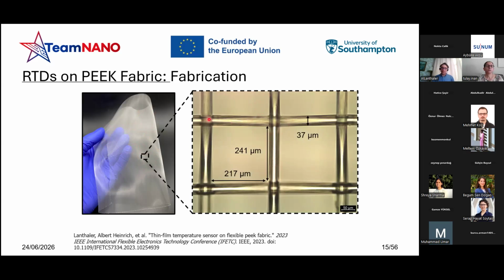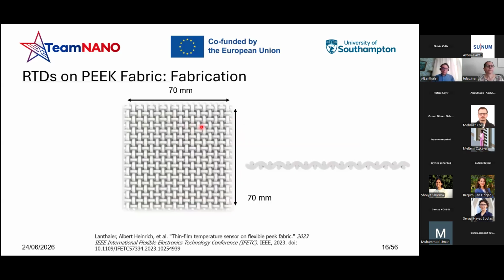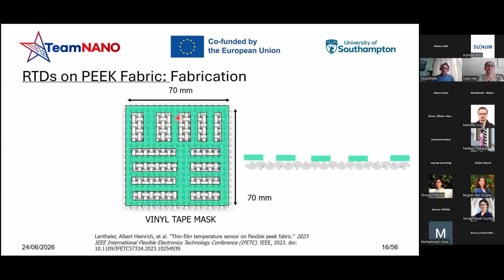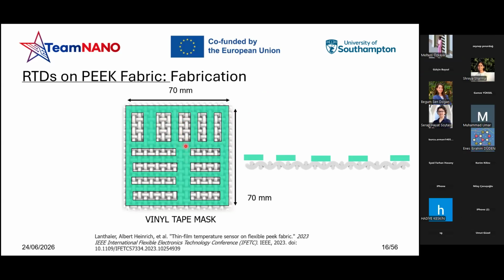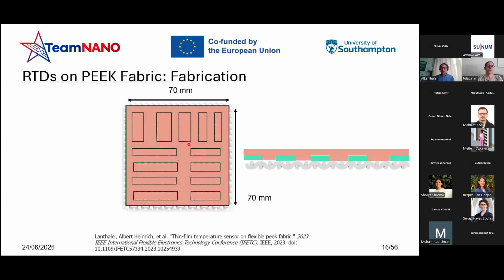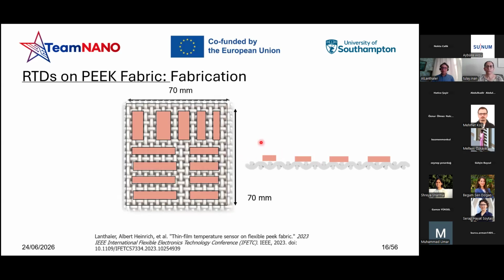As you can see, the lattice of the fabric is very broad, so it is pretty challenging for us to fabricate a continuous and smooth thin layer on top of this fabric. So what I've done, basically, I cut the fabric I mentioned before into a 70 by 70 millimeter square. I placed it into high vacuum condition in the sputtering tool. Before that, I taped it with a vinyl tape mask in order to have a better adhesion of the fabric itself and to avoid any sort of shadow effect on the very edge, but also because I wanted to be more free, speaking about customization of the mask itself. I deposited 300 nanometers of copper, and this was the final result.